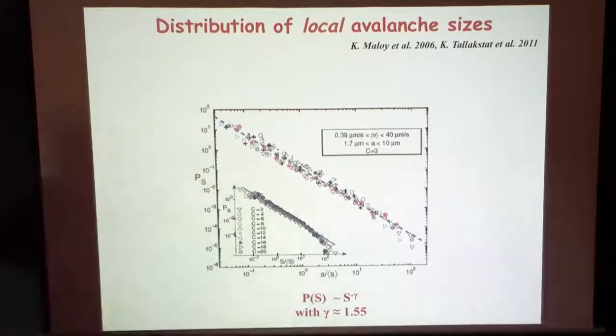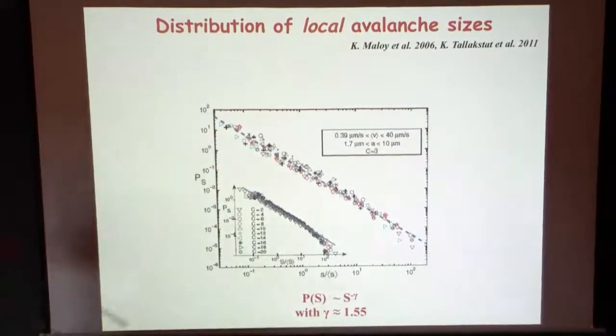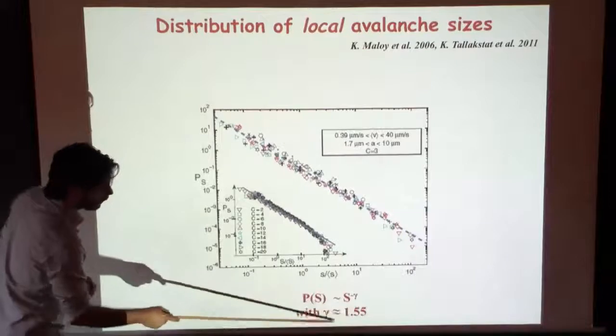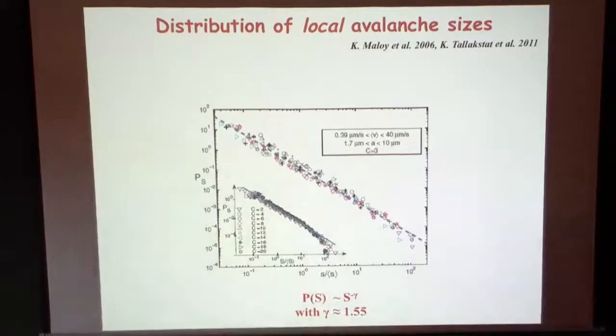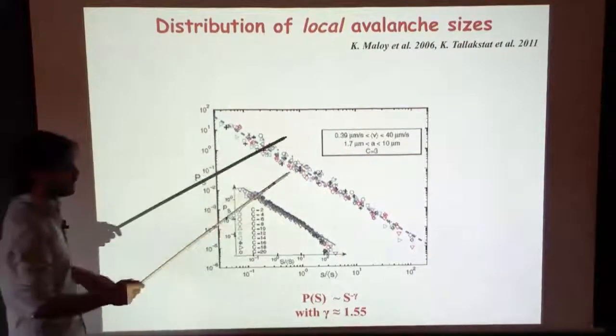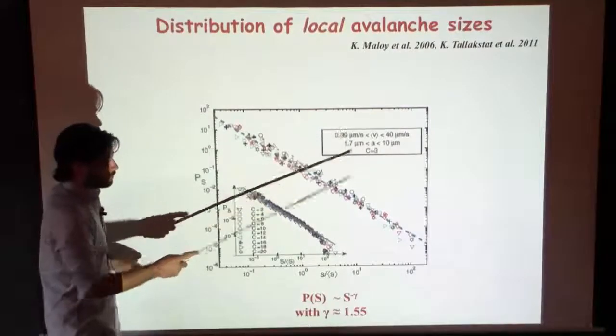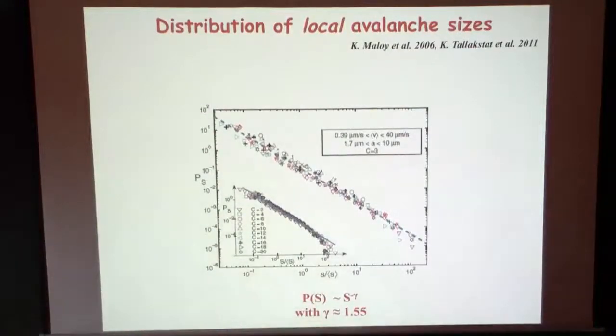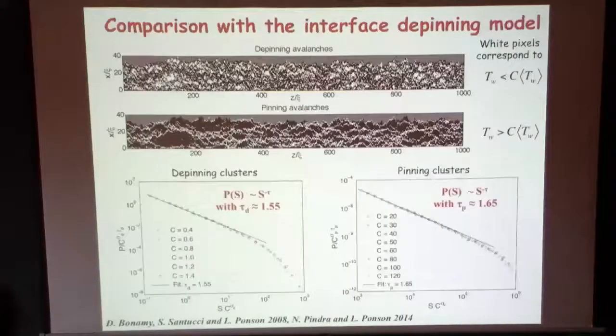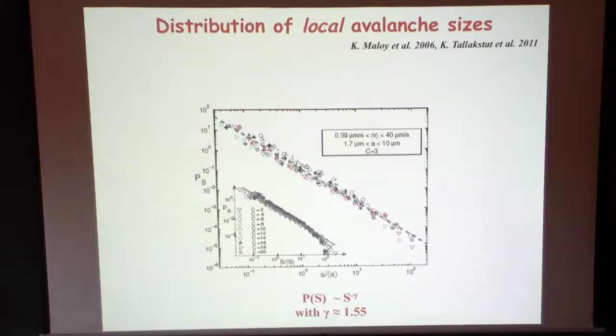The quantitative characterization of these clusters leads to power law statistics of their size. In particular, Knut and then further students showed that they were power law distributed with an exponent close to 1.55. In this experiment, they change the velocity, vary the pixel size, and play with the threshold, and this is a robust property. These are spatially connected clusters defined at the local scale.